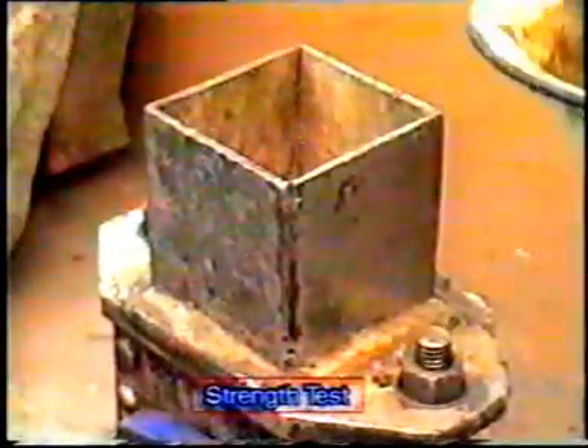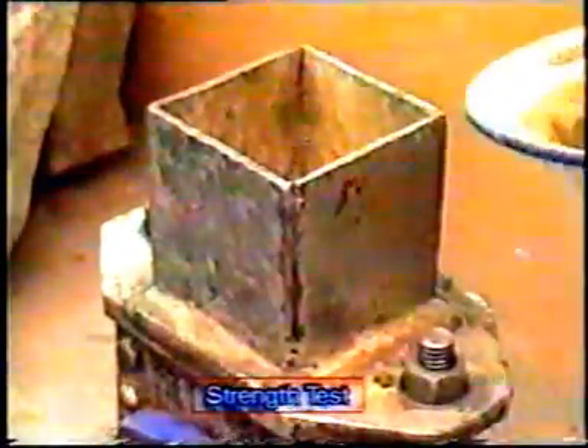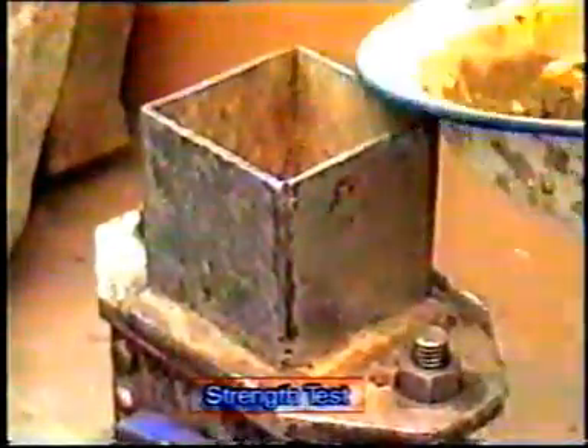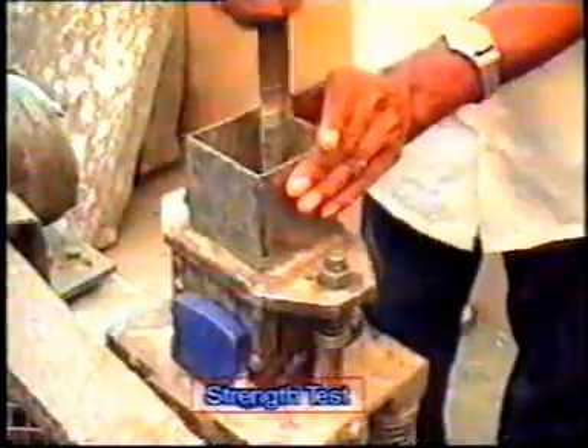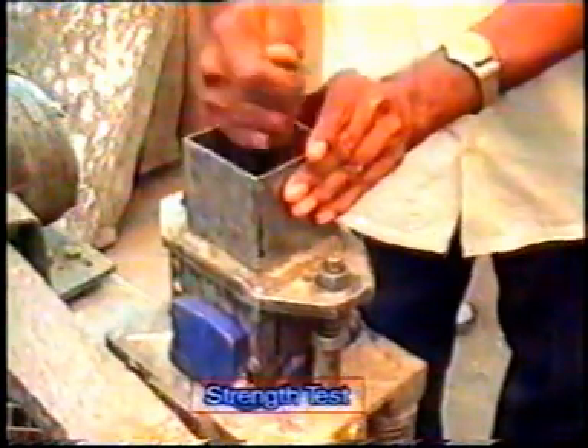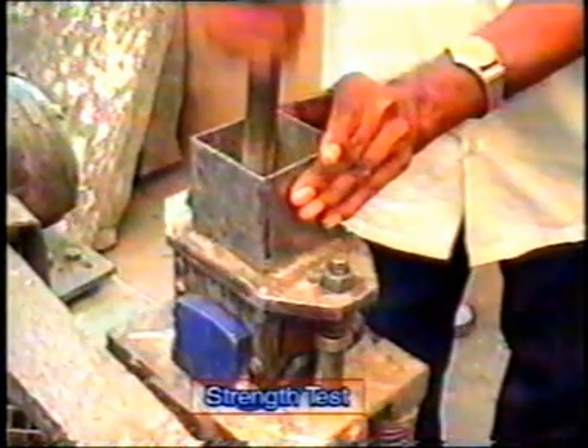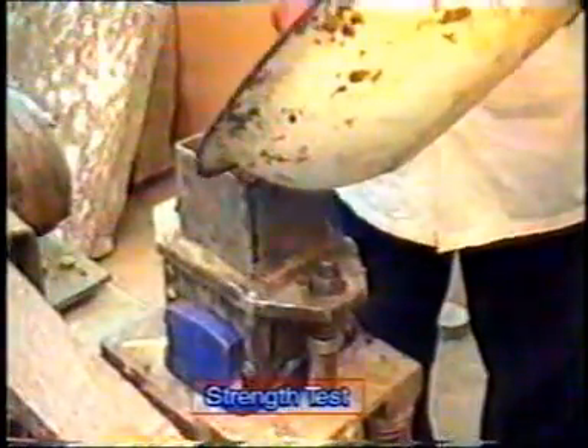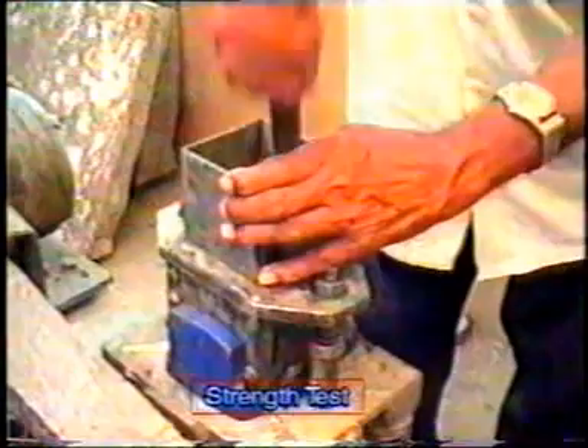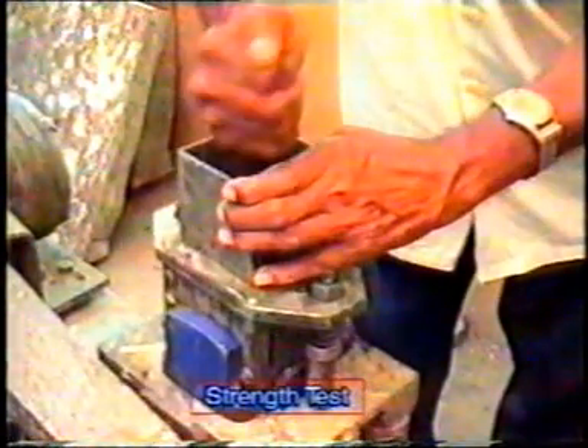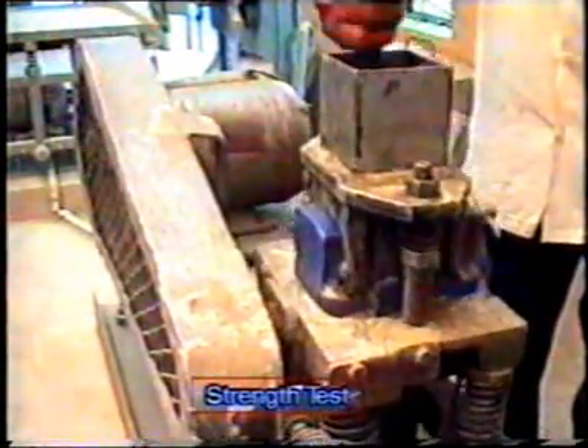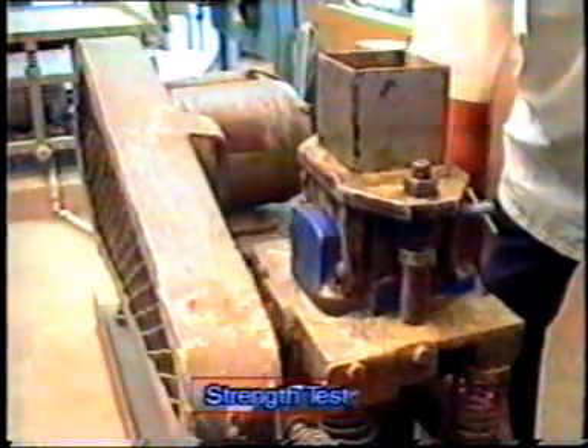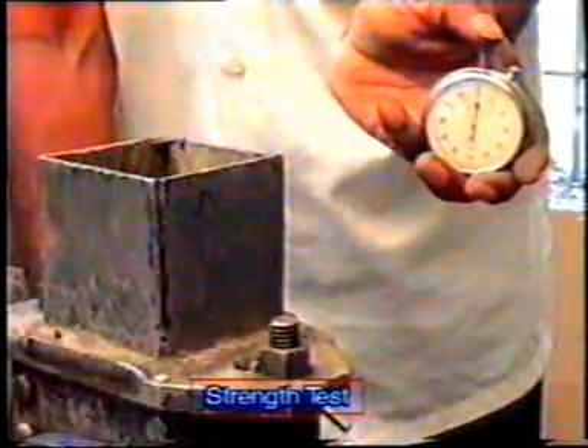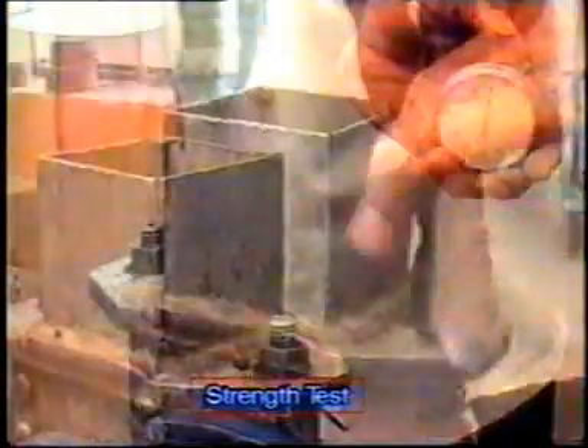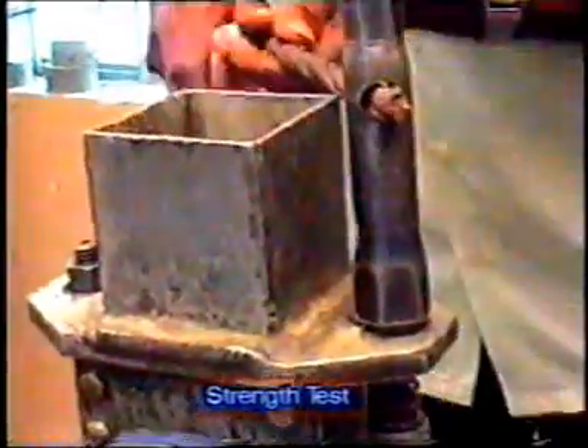Place the sample in the mold fixed on the vibration machine now. The mortar will be tamped with a rod for 20 times. Mix is placed again in the mold and tamp it again for 20 times. Vibrate the vibration machine for 3 minutes. Remove the mold with the base plate and smoothen the surface with a trowel.